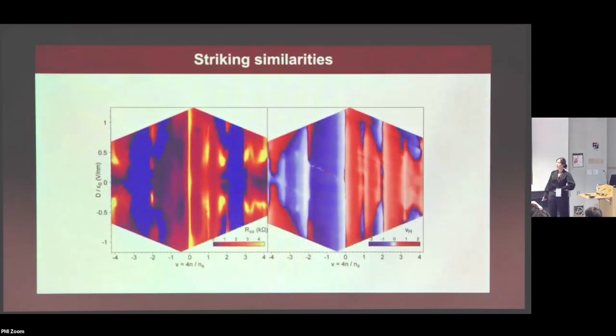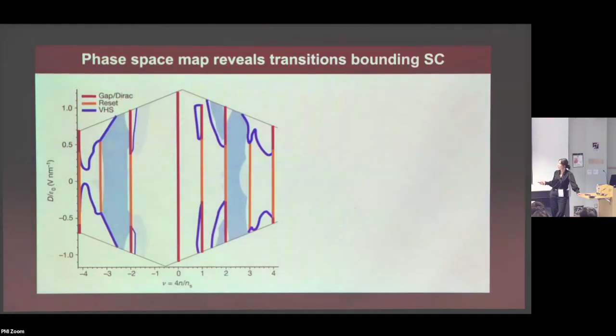Now we can compare side by side these two plots, the transfer resistance plot that we saw with the superconductivity and this hole density. Already you can see that there's a striking similarity just by literally looking with your eyes. We can't pinpoint exactly what, but there are some similar features. So we want to understand this more systematically, so we can put it into a single plot where the superconductivity is now in these light blue regions, and the hole density features are color-coded with different colors.